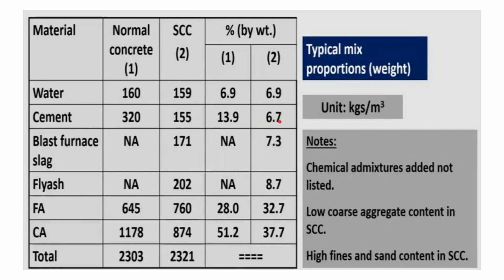However, SCC contains blast furnace slag, again almost 7%, and fly ash, around 9%. So 9 plus 7 plus 7 is around 23%, but in the case of normal concrete it is only 14%. So you can see a difference of almost 10%. That's why the filling material, the fine material, is quite high.